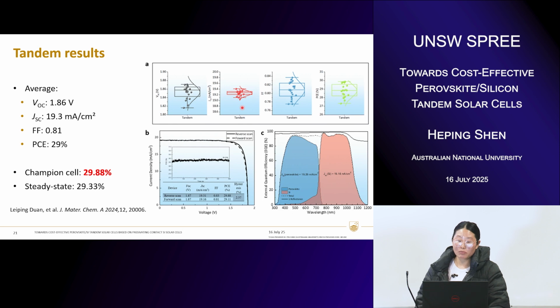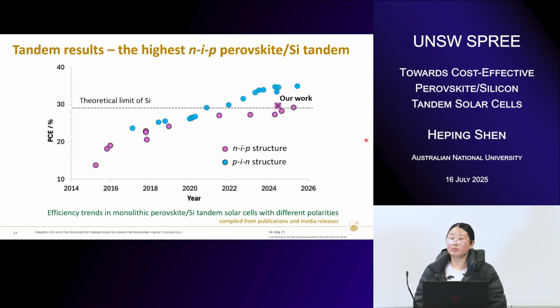Okay, so then we moved on to applying this cell structure into the tandem using the NIP cell structure. And we were able to produce quite impressive efficiency based on the double-side poly and also the NIP cell structure. Particularly, we were able to demonstrate a current density of above 19, which is significantly higher than most of the cell structures using spiro-OMeTAD, which is 17 or 18. And the fill factor is quite attractive. So over 29% efficiency, that was the highest for the tandem based on double-sided poly, but I would also like to share that that's also the highest performance based on the NIP perovskite cell structure.